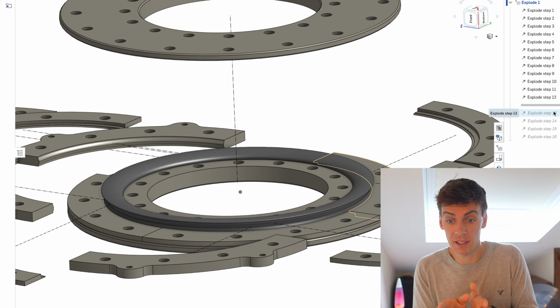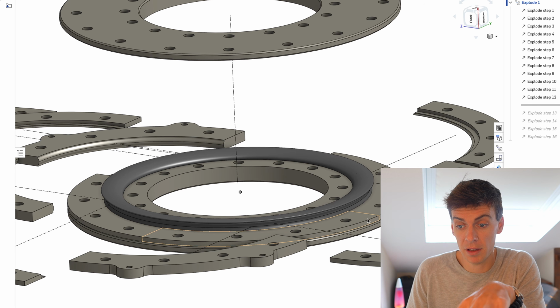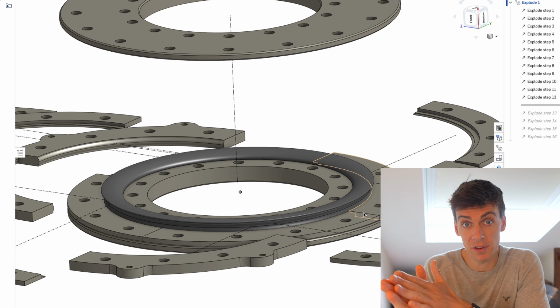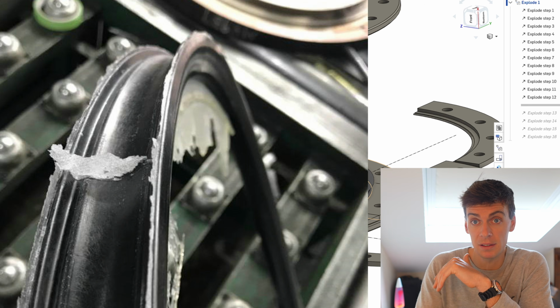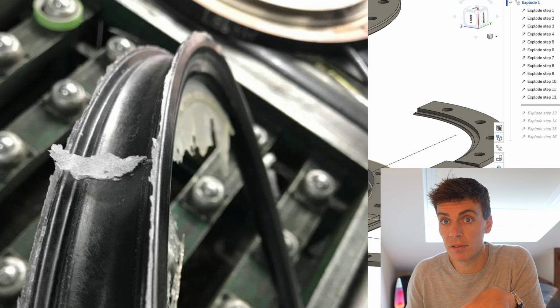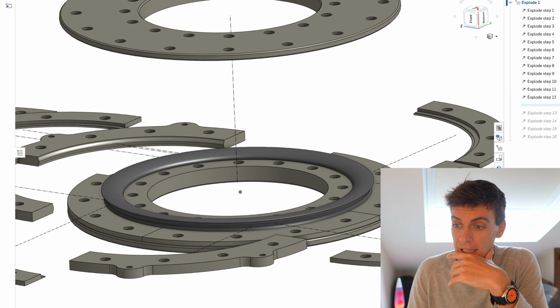So you get a lot of resin going down these grooves, because none of these interlocking or mating faces in this mold are sealed with O-rings or anything. They're just metal on metal, so you will get resin flowing down these gaps, trying to purge out. And that's really not good, because when you get a pre-preg fabric, you are starting with a set volume fraction of fibers to epoxy, and that's set for the strength of the pre-preg. If you are losing epoxy out of that correct ratio, you're taking away from the final specification, and from the strength the pre-preg should have when cured.